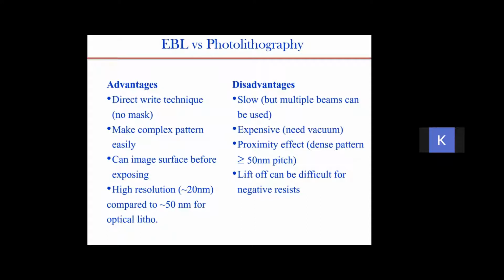There is also a proximity effect, and that's why the pitch, meaning the distance between two patterns, should not be less than 50 nanometers. That's another problem it faces. Sometimes it also faces difficulty with lift-off when you are using a negative resist. But compared to photolithography, it has a lot of advantages, mainly in resolution and also in making complex patterns.